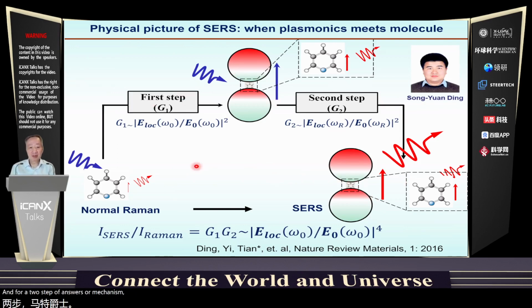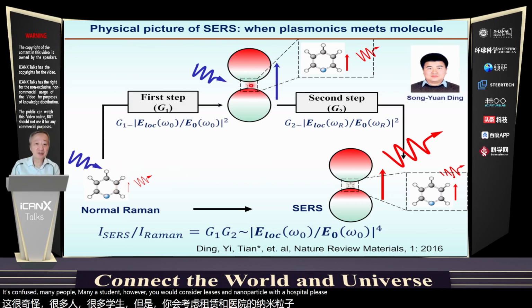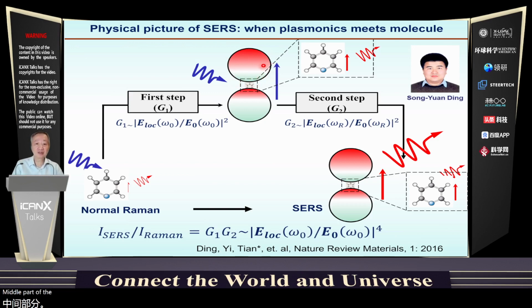SERS mechanism. Because if we simply correlate normal Raman to surface enhanced Raman, it confuses many students. However, if we consider a nanoparticle with a hotspot, please notice that this is not correctly proportioned because the molecule is much smaller than the nanoparticle. The nanoparticle is about 50 to 100 nanometers, and the molecule just 1 nanometer or smaller. And as you can see, if we have a plasmon resonance, the nanoparticle can absorb energy and introduce it into this hotspot, which means the light is much more efficient because the cross-section of this nanostructure, including the molecule, is much larger.